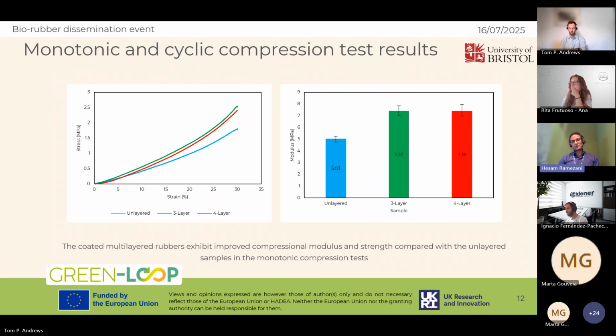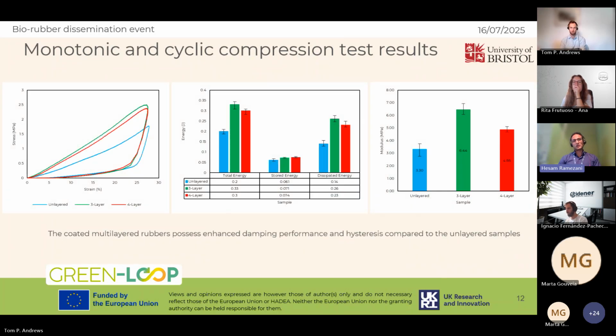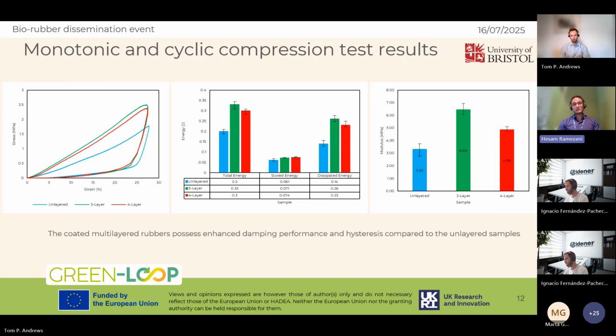In the next slide, you can see the cyclic compression test results in which the multi-layered samples show more hysteresis. The hysteresis is the area inside the loops, as you can see, and also a higher stored energy, higher dissipated energy, and also modulus. I need to mention that the 3-layered sample has a better performance in terms of monotonic and cyclic compression compared to the other 2 samples. Next slide, please.